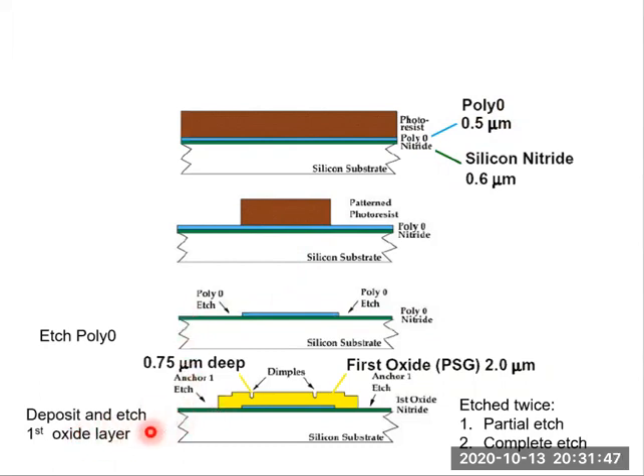Then deposit and etch the first oxide layer, or first PSG layer. Note that here oxide stands for PSG, phosphosilicate glass. This yellow layer represents the first oxide layer, which is 2 micron thick. And it's etched twice in this step. The first etch is a partial etch, which etches 0.75 micron deep dimples. So we etch 0.75 micron deep dimples on this first oxide layer.